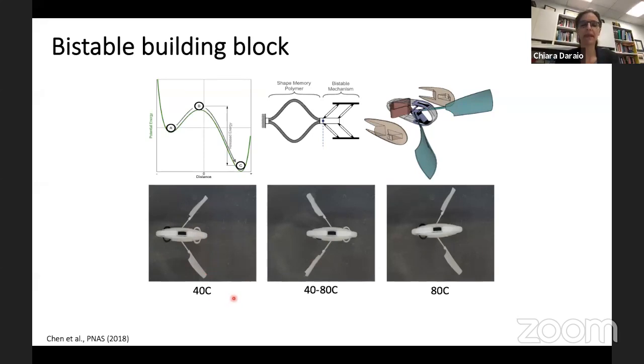You can see it in a bath of water, it's floating, and you can see that as we keep the water at a relatively cold temperature, the element is in the A configuration. As the temperature is increased, we're effectively using temperature to provide this hump in potential energy. And then finally, it triggers the bistable mechanism, which is effectively a swimming motion of the paddles in the front. And you see the little floater propelling forward. We can then reload by using a different actuating spring. If you pay attention here, there's a white one and a black one, which has a different actuation temperature and will reload the mechanism to the starting position.